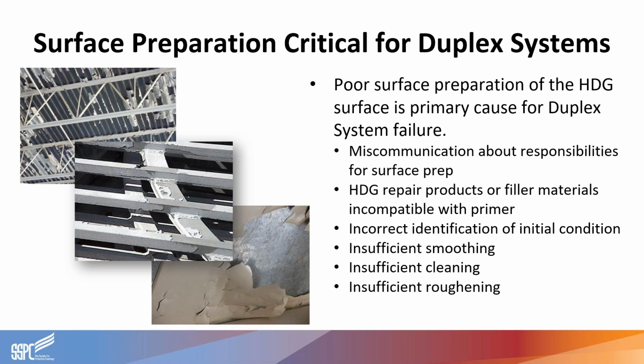So these conditions are not acceptable if you're looking to coat over the galvanizing. An even bigger problem is that it's very unlikely that either galvanizer or paint party was aware to price in the extra work needed to elevate the galvanized surface finish to the point where it's going to be acceptable to paint over. Practically speaking, these intermediate steps between galvanizing and surface prep for painting might not get discussed on a project by project basis. And when that occurs, some of these critical galvanizing surface preparation steps that I've listed here, like proper selection of repair materials, sufficient smoothing and cleaning before painting, all of these types of issues may end up being performed to a lower quality standard or just completely skipped entirely.